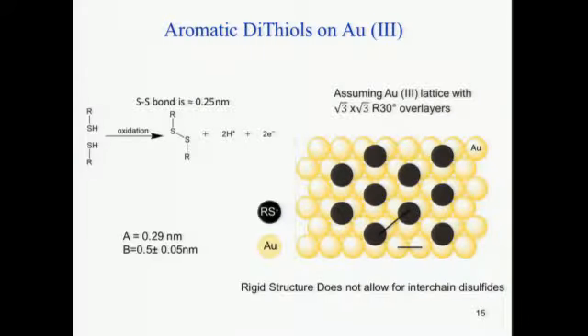Well, the disulfide bond has a bond length of about 0.25 nanometers. But if you look at how the alkane thiols arrange themselves on the gold 1,1,1 surface, there are some possibilities of where the disulfides could meet each other. But those possibilities are larger than the disulfide bond.